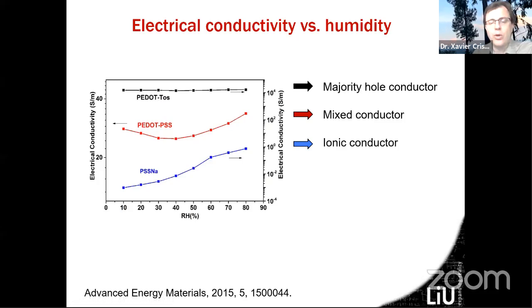So it's a drastic effect when you promote ionic conductivity when you have humidity around, of course, because the mobility of those ions is just boosted. Now, if you look at the PEDOT:PSS, which is the mixed conductor, at a low humidity level there is still mostly the electronic carrier that is dominating. But when you increase the humidity, what is happening is that there's a decrease and then there is an increase of conductivity, meaning that the ionic conductivity starts to have also an impact in those materials. Also, the presence of ions and water is changing the potential landscape of the electronic charge carriers in that material too, so it can be quite complex.